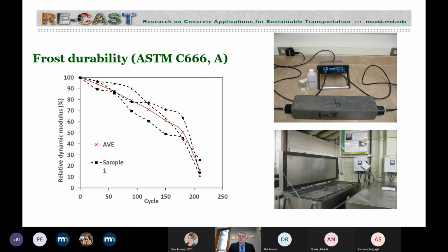This is the accelerated freeze thaw test, procedure A of ASTM C666. That means freezing and thawing in the presence of water. So it's a severe test. And you have here in red the average of 3 samples, and you have the relative dynamic modulus of elasticity that is determined using P waves. And then you see the cycles up to 200 cycles.